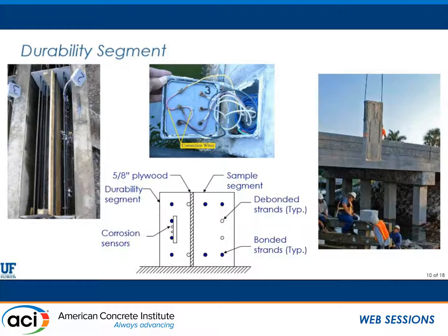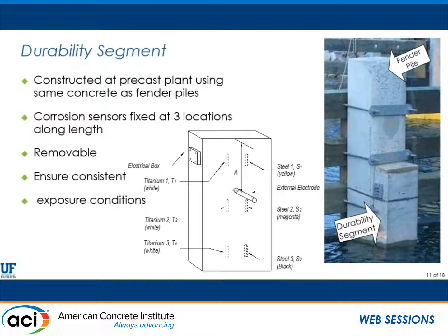So then they allow us to get the electrodes or the corrosion sensors all at the same elevation. So, with the tidal fluctuations, for each of the different materials we're getting the same elevation, because corrosion rates, of course, are going to vary depending on if you're in the tidal zone or the splash zone. And so it's very important to maintain that consistency.